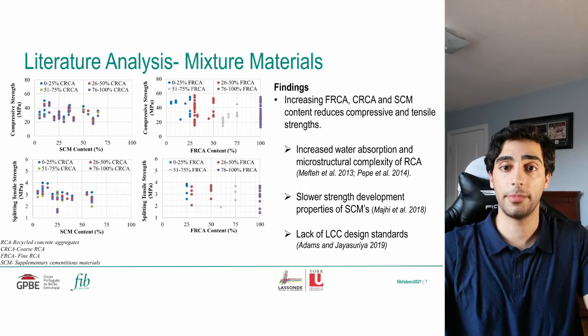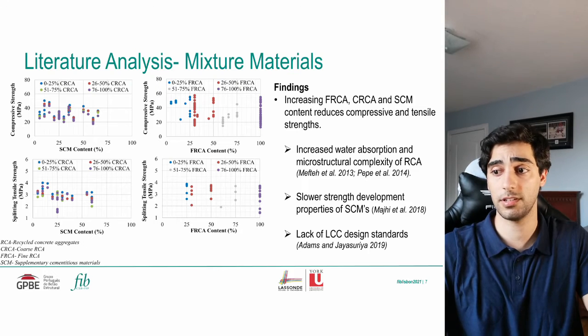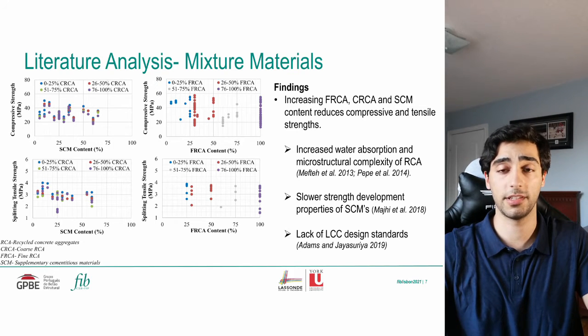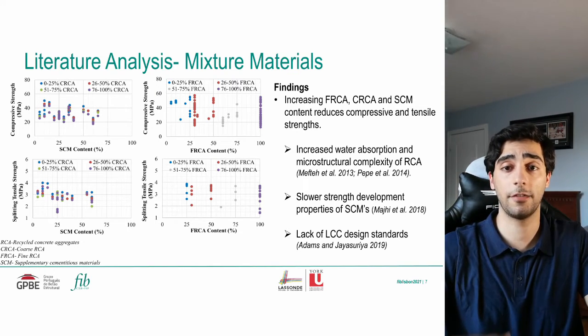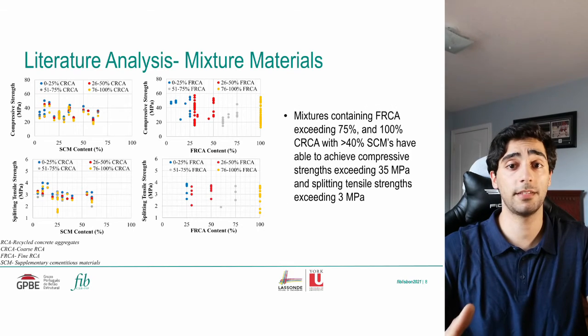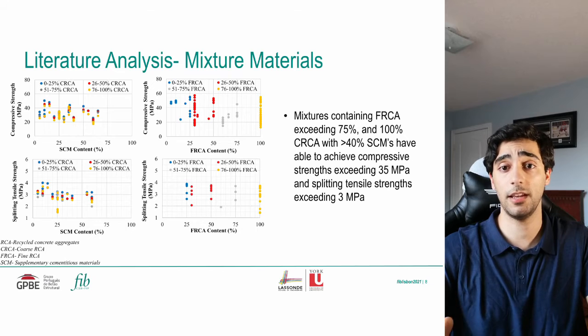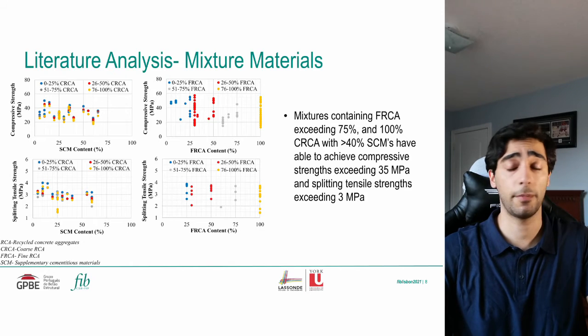Many of these reductions are attributed to the water absorption properties and microstructure complexities of the RCA sources, the slower strength development properties of SCMs, as well as the lack of specific design standards for the production of low-carbon concrete. However, based on the results, mixtures using fine RCA with content of over 75%, or mixtures with 100% coarse RCA and 40% SCMs have been able to achieve compressive strengths exceeding 35 MPa and tensile strength exceeding 3 MPa, indicating the structural capacities of these concrete mixtures.